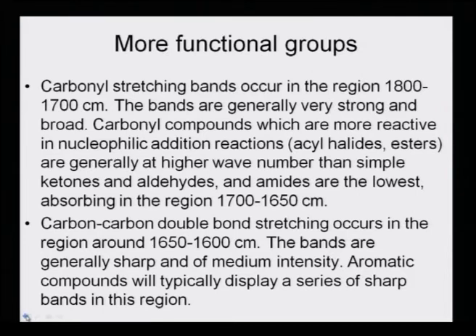Carbonyl compounds which are more reactive in nucleophilic addition reactions, acyl halides and esters, are generally at higher wave number than simple ketones and aldehydes, and amides are the lowest absorbing, in the region of 1700 to 1650 centimeter inverse. Now, you see that as we go along, different types of carbonyl compounds like acyl halides and esters have a higher wave number, and then the simple ketones and aldehydes, and the amides have the lowest, at the other end, which is between 1700 to 1650. So, in a way one can imagine that carbonyl ranges from 1800 to 1650.